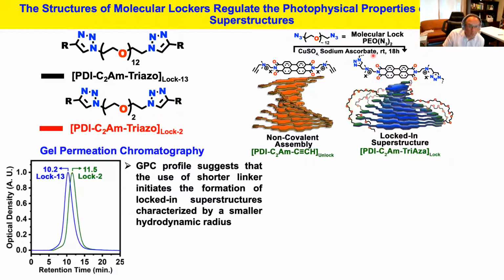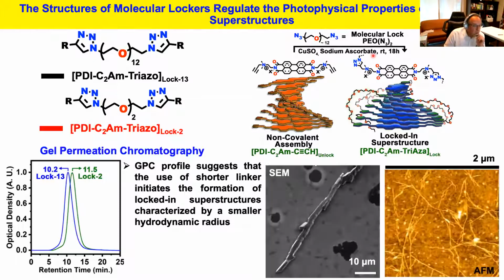Now, of course, if we probe the size of this nanoscale object using gel permeation chromatography, we realize that we are dealing with an object that has a smaller hydrodynamic radius. In many ways that makes sense, because the shorter tether has a lower degree of structural freedom in solution. We have also probed the solid state morphologies of these materials using both SEM and AFM. You can see that you are essentially forming what I would argue is a crystalline material in the solid state simply by drop casting them on any type of solid state substrate.